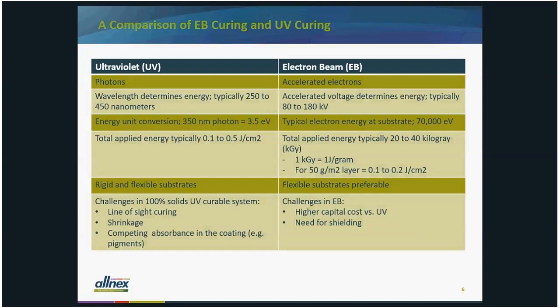If you want to look at how they compare on an energy unit conversion basis, a 350 nanometer photon has about 3.5 electron volts of energy, whereas electron beam is a lot higher. However, if you look at the total energy applied in, say, a 50 gram per square meter layer of coating, the two processes come out to about the same total applied energy. UV works well with rigid and flexible substrates. Because of the shielding that's necessary for electron beam equipment, it's a lot easier to use flexible substrates, so they're preferred.